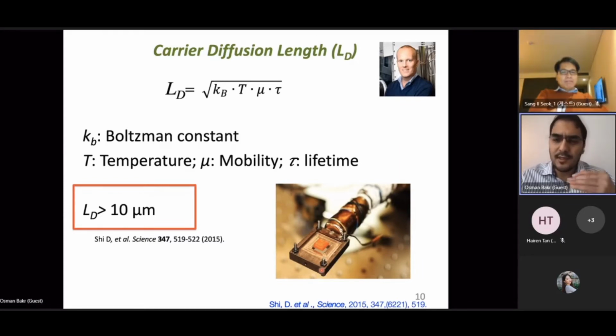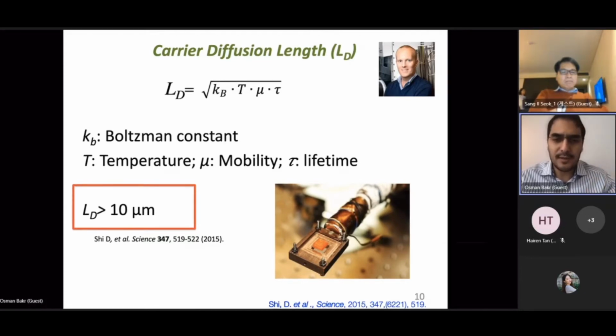And so we measured the mobility of the material, we measured the lifetime, and we used the Einstein relationship to extract diffusion length. And at that time, we realized that the diffusion length was at least more than 10 microns. And that was a real surprise, because at the time people who worked with polycrystalline solar cells estimated that diffusion length was a few hundred nanometers. So this created a much bigger expectation in the field, an expectation that this material can do a lot more than what people think. So the second step for us was, what can we do with single crystals?